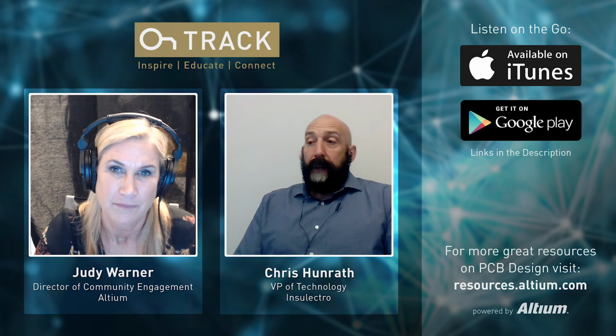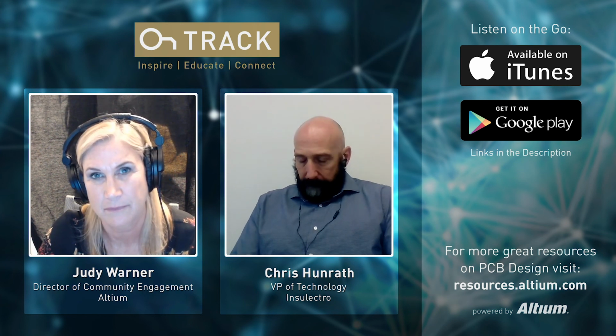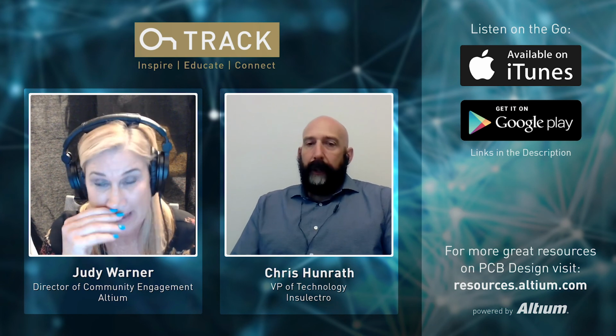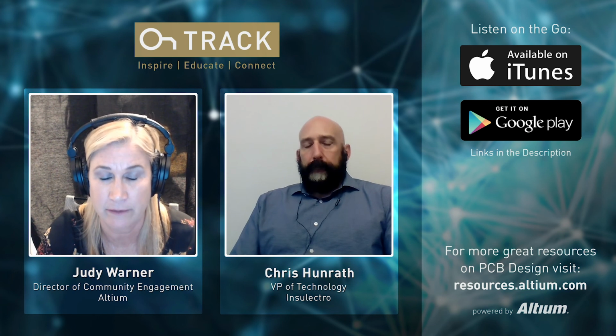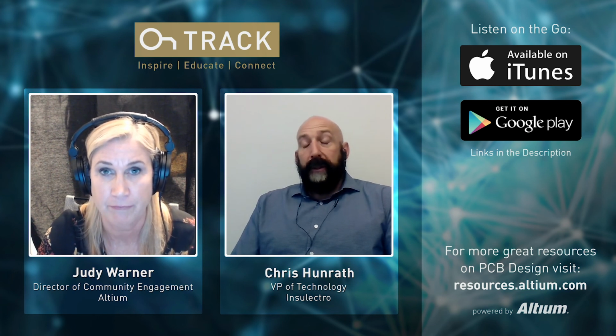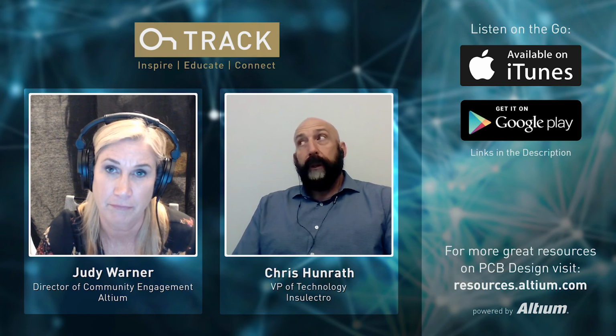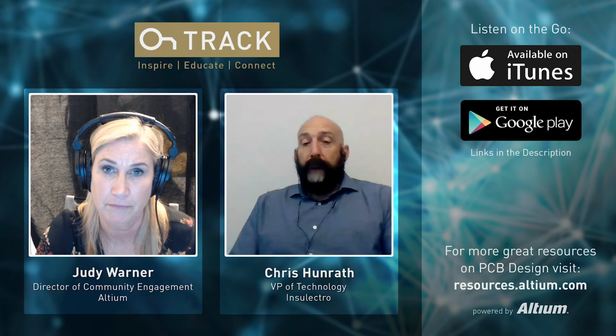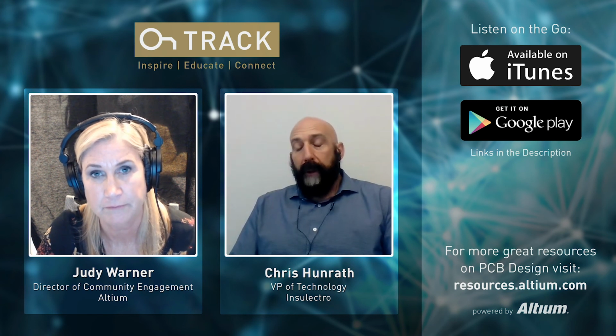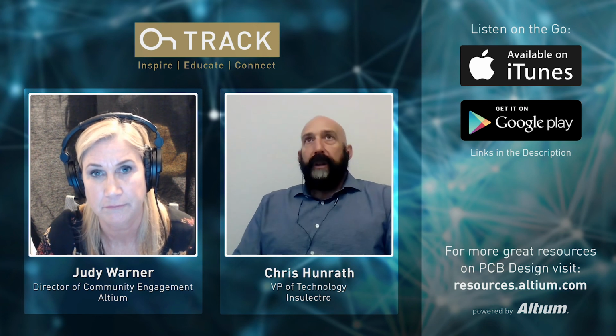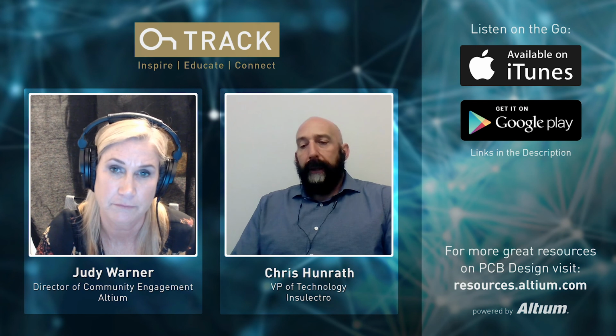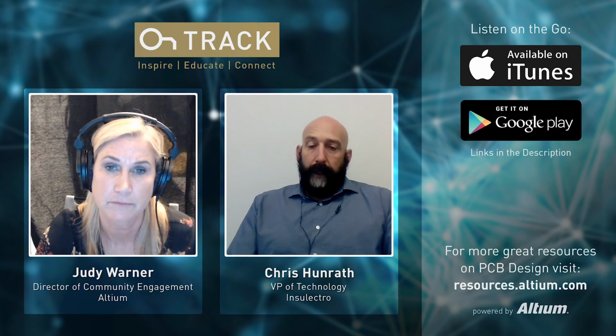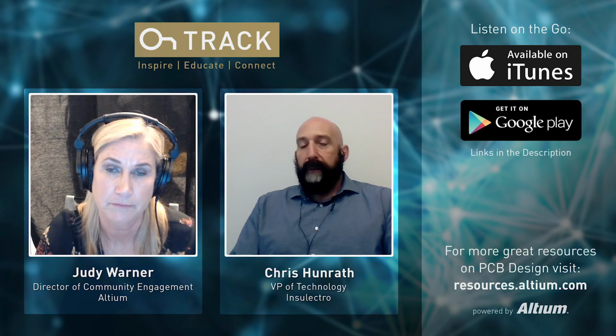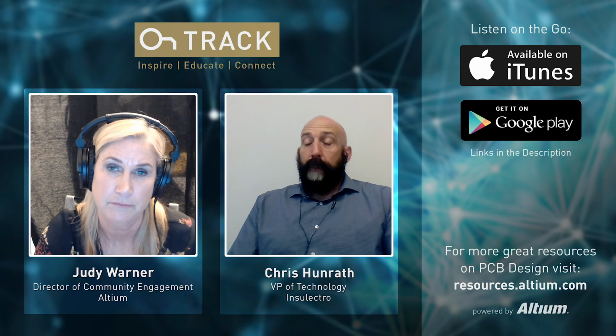In fact, there was a great study done recently with HDPUG, and I don't know if your listeners are familiar with HDPUG, but we'll share that link below in the show notes, because they're an amazing asset to our industry. They did a great study on crosshatch ground planes on flex. There are some performance trade-offs with crosshatch ground planes, but they create a window for moisture to get out. Moisture will get in more easily, but it can get out more easily, as opposed to a solid plane. And there is a frequency cutoff where that is usable. One of the things the study looked at was diamond-shaped versus round openings in the ground plane. But I always like to recommend putting openings in the ground plane when you can afford it, just as a moisture egress.